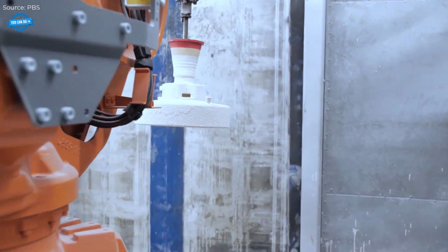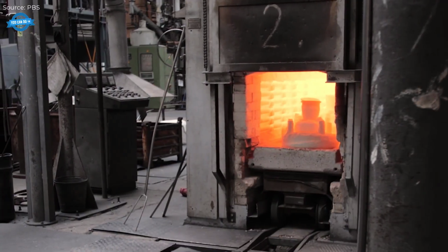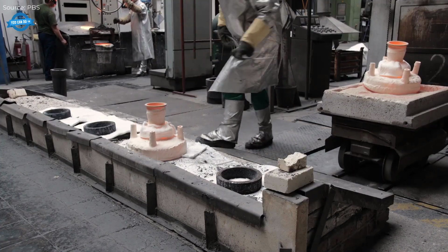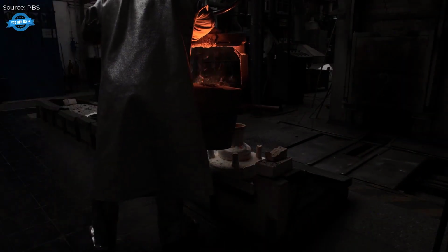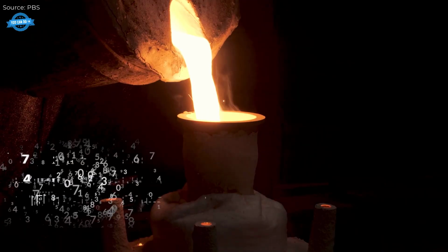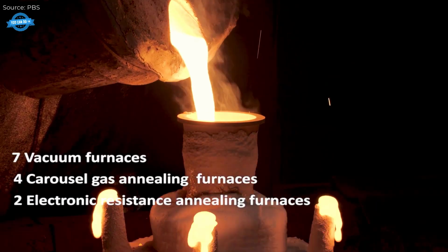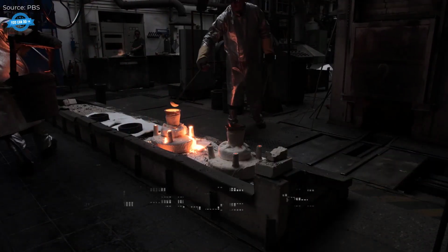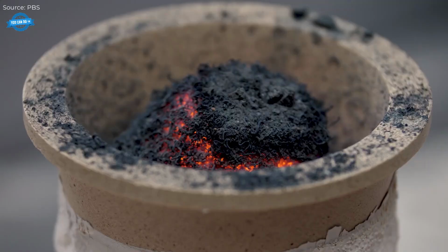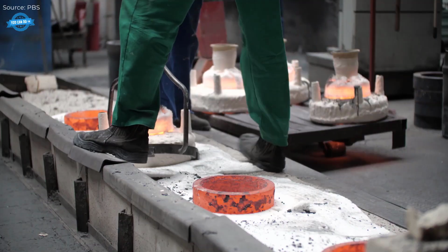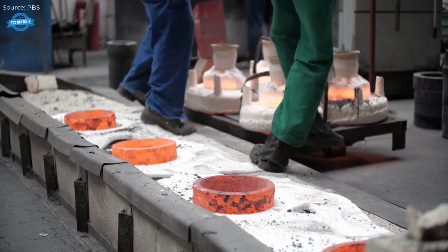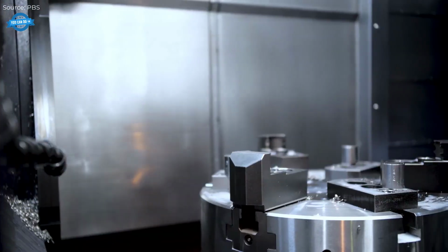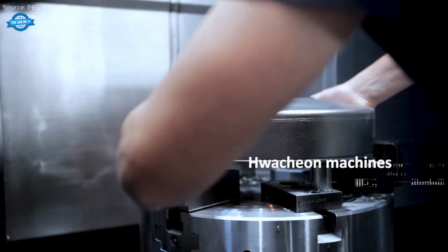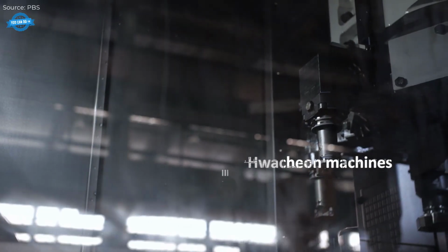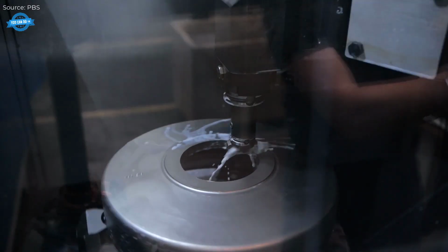Once the ceramic mold is robust enough, it undergoes high temperatures, preparing it to withstand molten metal. When the nickel or cobalt-based alloy reaches the required heat, it is poured into the mold, filling every intricate detail. After cooling, the ceramic shell is broken away and the casting is freed. The spinner disc then undergoes thorough cleaning, often using stainless steel shot blasting, ensuring it meets high-quality standards for use in glass wool production.